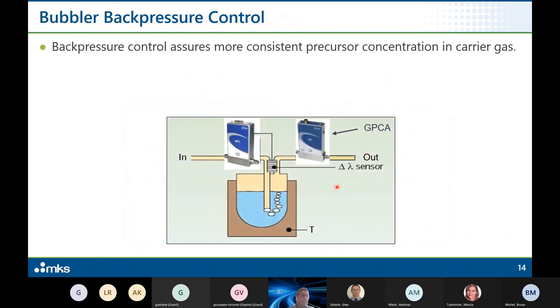Another application for the integrated controller is a back pressure control of a bubbler, where you try to get the vapor pressure, so you add to the incoming gas the vapor pressure of this material which is in the bubbler. And to get a very constant precursor concentration, it's good to have always the same pressure in the bubbler. Obviously, this is already a downstream control, no longer an upstream control, because the controller for the pressure sits between the bubbler and the chamber, so it controls the pressure downstream of the bubbler.